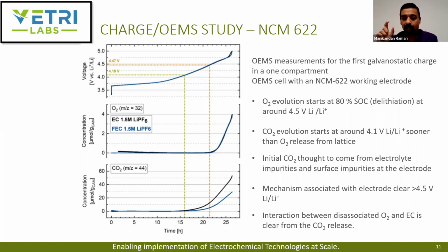So there's obviously a contribution to your surface impurities and how your quality on the electrode is and the electrolyte is, so there is some contribution just from that itself that causes the impedance rise. And further, there's obviously the oxygen, the lattice oxygen release, contributing further to the cascading effect, that actually accelerates that impedance rise as well. So there's definitely two different things.